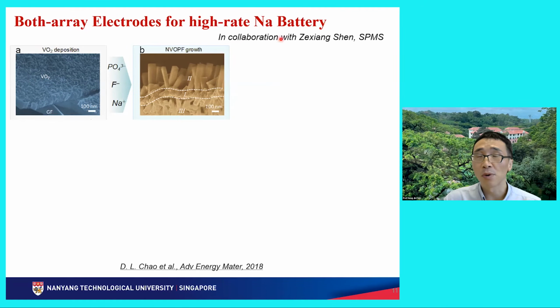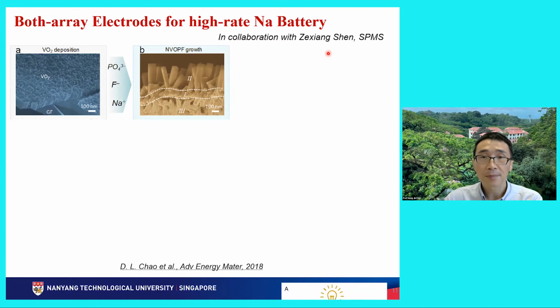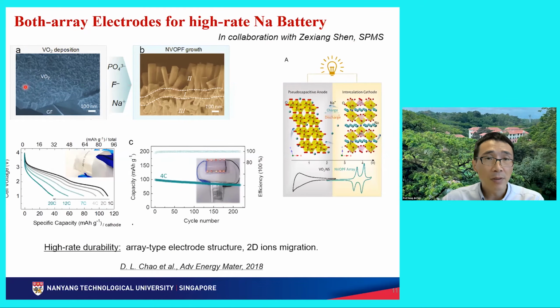This was done in collaboration with Shen Zexiang at SPMS. So we get an anode and we get a cathode. The uniqueness here is that we grow the active materials directly on the three-dimensional graphite foam as current collectors. So we can assemble full batteries. This is a so-called pouch cell, a thin film battery. Then we characterize the battery like that. It's not like the conventional powder battery that has a very evident plateau for discharging. However, there's a more sloping discharge, which means it behaves more like a capacitor. That's why we call them hybrid batteries.